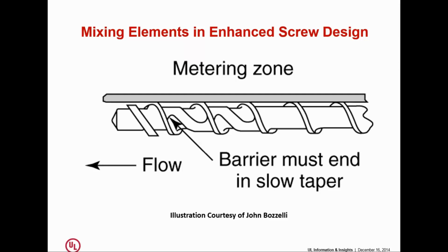And it made such a deep impression on our operations people that over the course of the next 5 years, we replaced virtually every screw in the plant with a mixing screw. We no longer had general purpose screws in our plant anywhere. And the number of so-called processing problems and the number of so-called material variability issues that simply disappeared was absolutely remarkable. And this is one of the reasons I'm talking about this today, because most people never have a chance to experience the difference between doing it the way we've always been doing it and doing it with this modification in the hardware that allows us to get out of the very same materials much, much different results.